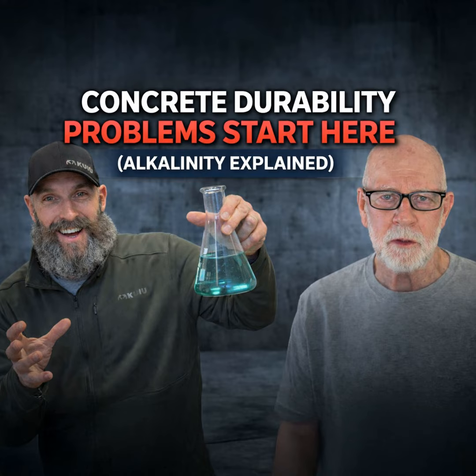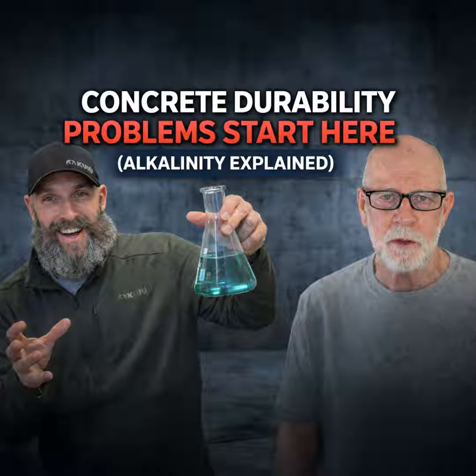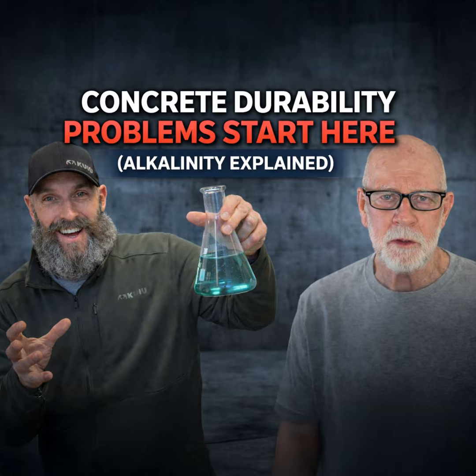And I'm absolutely positive that's what's causing the self-desiccation that we're seeing now, because there's not enough moisture available for the cement formation. And the reason why that happens: when the cement is initially initiated, it uses up some of the water. Well, now that they have limestone and all these other little particles in there, to properly dampen those, they're actually competing against the clinker to form cement. It wants water and wants to get wet. The clinker wants to get wet, but there's only so much water to go around.